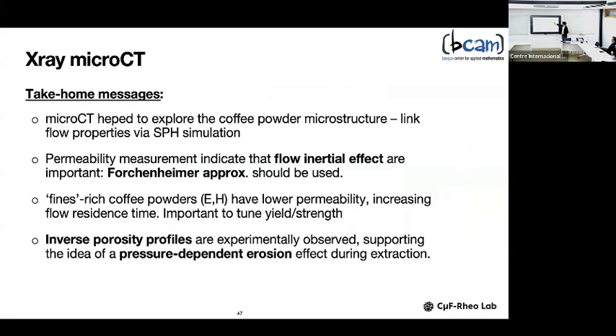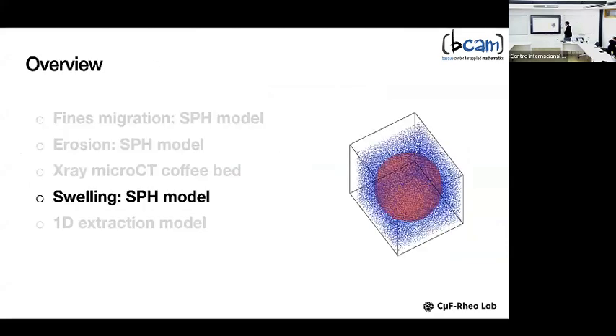So the take-home message here is that flow inertial effects are important. They can explain pressure-drop-dependent permeabilities. And the other thing is that inverse porosity profiles are also observed experimentally, and we believe that this is related to a pressure-dependent erosion, not to mechanical failure, but to the detachment of fines adhering to the surface of the coffee particle.